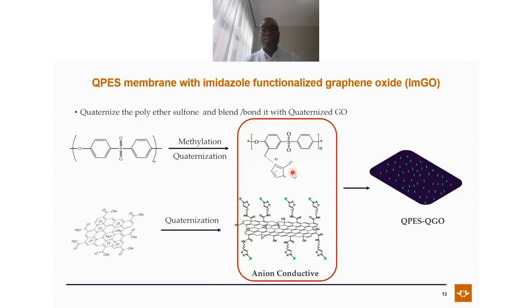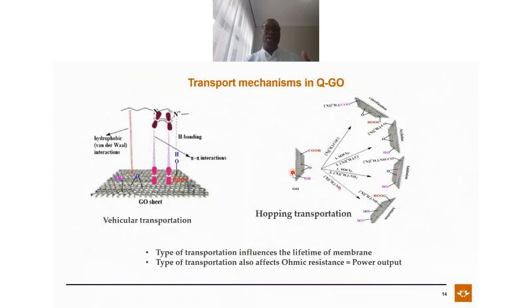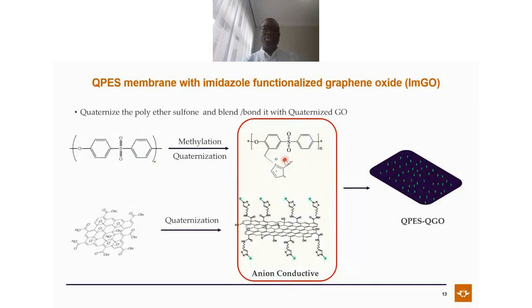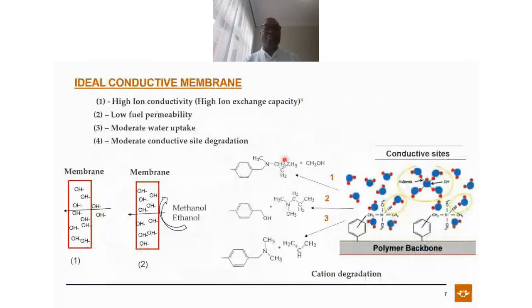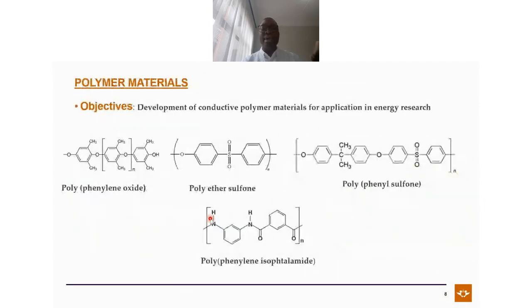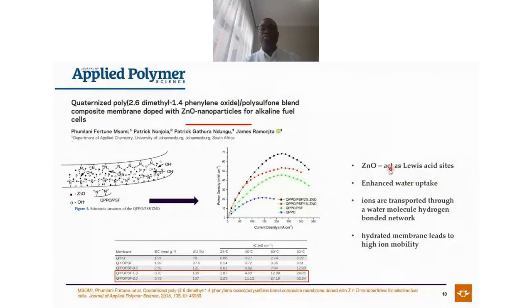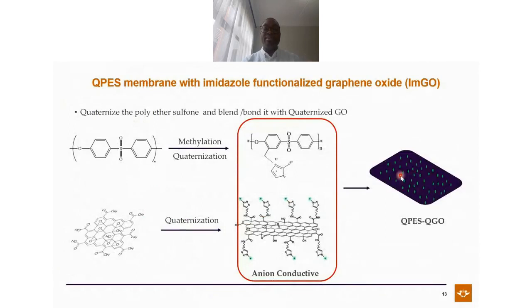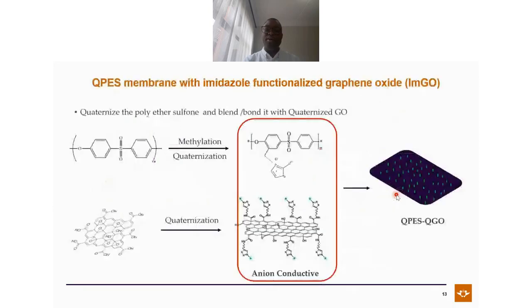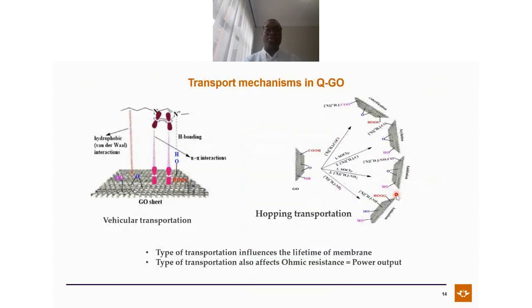We took this membrane after we designed it. Remember, this and this are quaternized. We wanted to see the transport system. Remember, on our previous slide, we said the membrane is able to conduct here, and it can be transported in terms of water and also in terms of hopping. What we found out when we quaternized both the membrane and the filler in the study was that the material suddenly has two modes of transportation connectivity. Remember, normally the material is either going to have what we call vehicular transportation of OH, or it's going to have hopping transportation of OH. But we found out that if we quaternize both the membrane and also the filler, you put both transportation mechanisms in control.